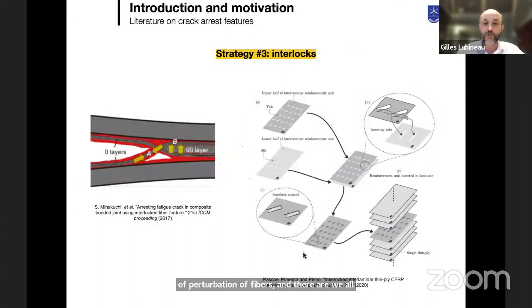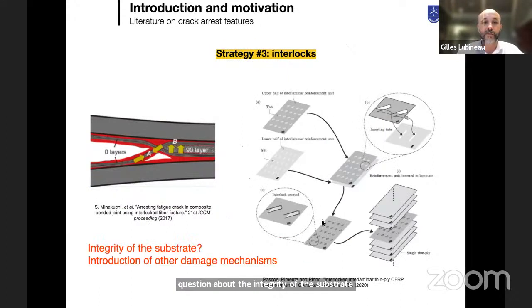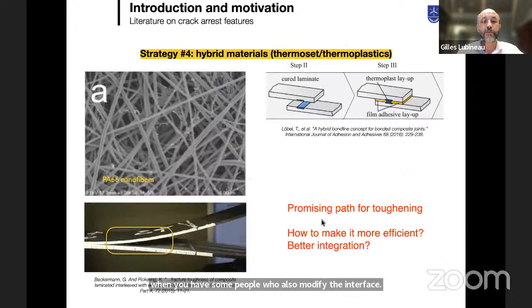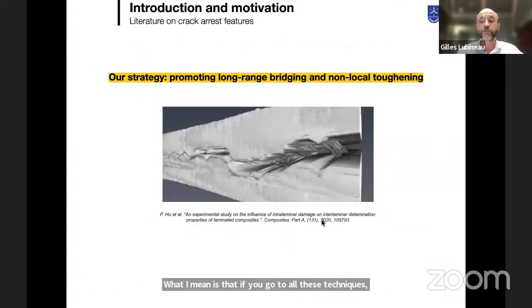Then you have some people who also modify the interface. What I mean is that if you go through all these techniques, what is important to understand is that they all modify a lot the substrate, and they all modify a lot the quality of the substrate. So what we want to do here is to introduce a new technology to reinforce the interface that is based on a single strategy that is about promoting long-range bridging. That means when you have delaminations, we are going to try to reinforce the interface by introducing these fibers that are going to bridge from one substrate to the other one and introduce what you call non-local toughening.